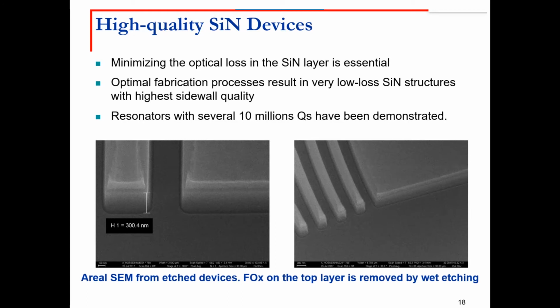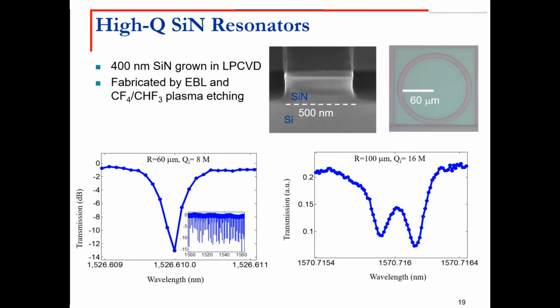This is an example of a fabrication process we developed where you can get very good sidewalls with a very low amount of roughness. This is a mask that is used, a flowable oxide mask on top of silicon nitride, which eventually will be removed by wet etching. But using that type of process, quality factors in the range of tens of millions have been achieved in silicon nitride. So that's one order of magnitude improvement. This is an example of a silicon nitride structure that can even be fabricated on top of silicon if needed. Quality factors of 8 million and 16 million for different radii have been achieved.